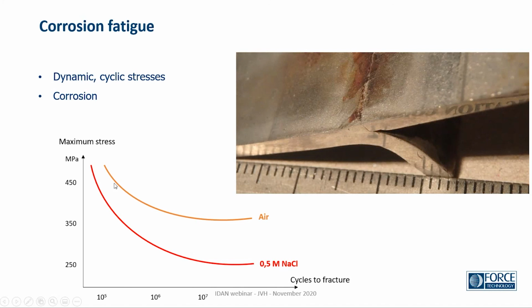An example here of fatigue in air without the corrosion, where we could have a stress level or amplitude of the stresses up to 380 or something like that in air. But if it's in a salt solution, it's not more than about 250. So it clearly illustrates how much difference corrosion does to fatigue, or might do.